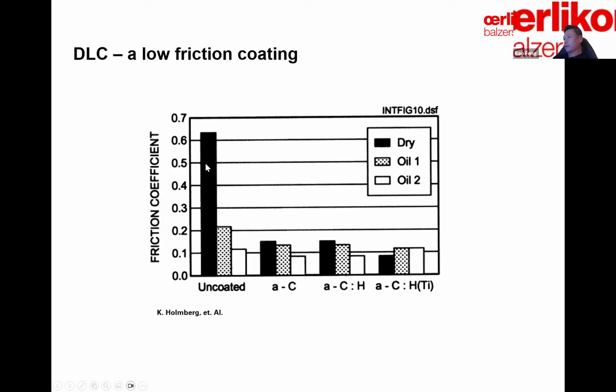The key point here is that with the DLC coating, you can bring the friction coefficient of the steel down from a 0.6 level to about 0.1 level. It's a similar reduction to when you apply traditional oils or oils with EP additives. So what that means is that for some dry contact conditions, you can use DLC to replace the traditional ways of lubrication.